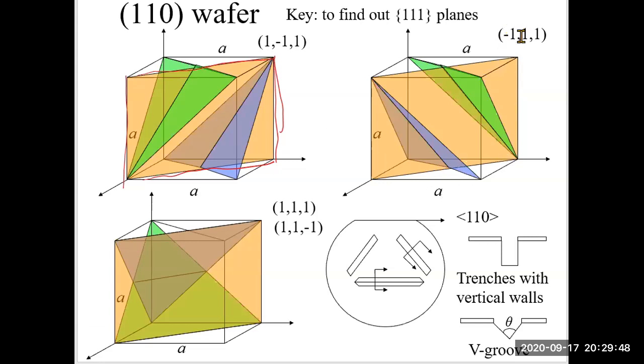Similarly, -1, 1, 1. This 111 plane cuts the negative x-axis and intersects y and z with equal distance. This plane is also perpendicular to the 110 plane. And the other two, 111 and 11-1, are not perpendicular to the 110 plane. So two are perpendicular and the other two are not. By taking advantage of these two perpendicular ones, we can fabricate trenches with vertical side walls on 110 wafer.